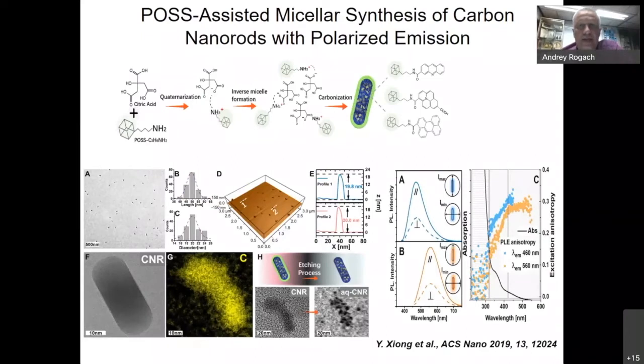So I still have a few slides here, and I know I have to finish my talk. So here I wanted to tell you that we can also control the shape of these materials. For example, if we synthesize carbon dots in so-called micelles, which are formed from this particular material, which we call POSS, which is shown here. So these micelles are elongated. And when we carbonize our precursor inside these micelles, we will end up with elongated particles, which we call carbon nanorods. You can see a photograph here. And these particles will emit polarized light along this long axis, which is pretty interesting for some applications as well.